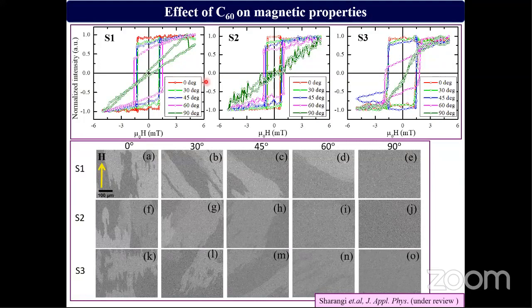So we have seen there is a change in the HC for all the samples. However, there is no change in the domain structure. So the change in HC may be the effect of the spin interface at the cobalt iron boron C60.